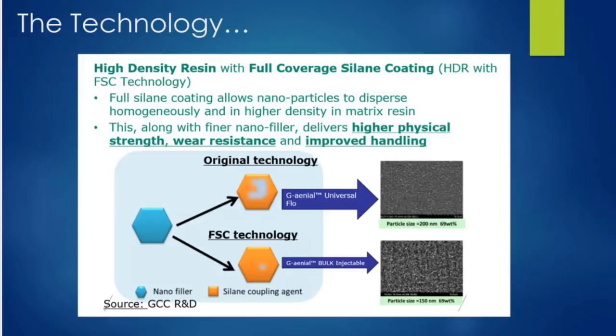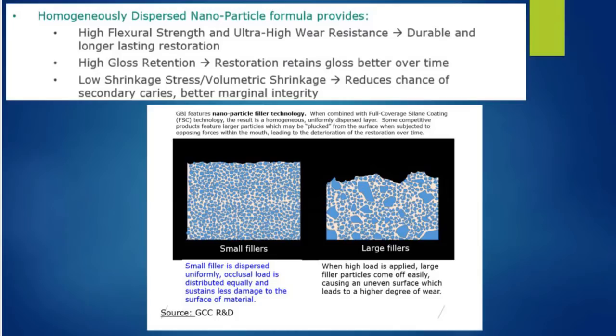So when we got the literature at first, I did read all about it, seeing that it was a high-density resin, very interestingly covered with a full silane coating. That allowed the nano-particles to disperse. We had a very homogeneous mix, very high-density mix. So it gave us a nice combination of both strength, wear resistance, and improved handling. So again, that's what they wrote, but was it really going to perform that way? It has very good flexural strength and good gloss retention.